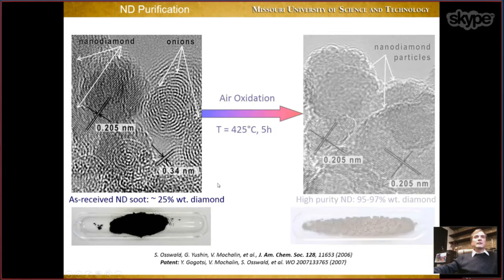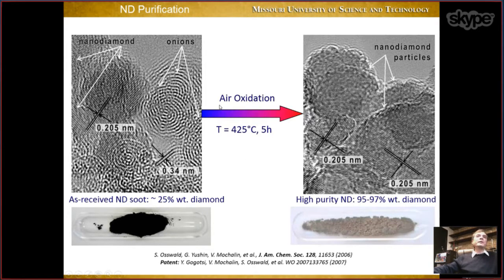We discovered in 2006 that this can be done by simply heating nanodiamond in air atmosphere. So imagine we go from all those aggressive liquids, nitric acid, sulfuric acid, hydrochloric acid, and so on, we completely eliminate them. We just heat material in open air. So the only reagent actually which is used in this technique is just oxygen from air. The key here is that you need to do it at 425. And this temperature is very sensitive, because if you go 10 degrees C above this temperature, then you start to oxidize diamond and you lose diamond. And this is not what you want to do, right? If you go 10 degrees C lower than this temperature, nothing happens, you do not purify it.